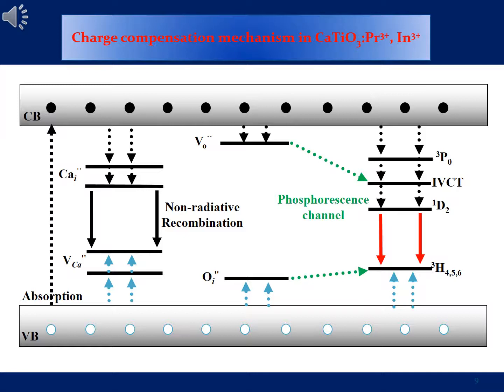Now, in our material, which is filled with a lot of defects, we will then be having defects corresponding to calcium, and defects corresponding to titanium, and defects corresponding to oxygens. Now, those of calcium and titanium which are positive, they will lie in the donor level, and the corresponding vacancies will be at the acceptor level. However, both calcium and titanium, they are very deep into the band gap of the material, such that when we excite the electrons and they are trapped into the states, then they will recombine with the corresponding holes non-radiatively.